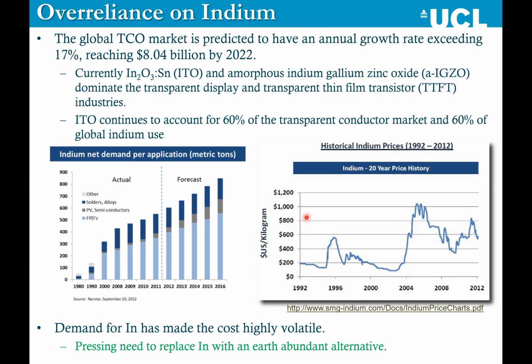But what this has done is made worse by the fact that indium is considered quite a rare element, and it is often found in places that you would consider to be geopolitically unstable. So if your local warlord has all of the indium under his control, then he can let it into the market however he likes. And this causes large fluctuation in the cost of indium over the last 20 years. This has created a problem for industry because industry would love to be able to set their profit margins, and they could even accept a small increase in the indium cost year on year because they could fix that into their margins. But not being able to predict how the indium price is going to fluctuate is quite awkward.